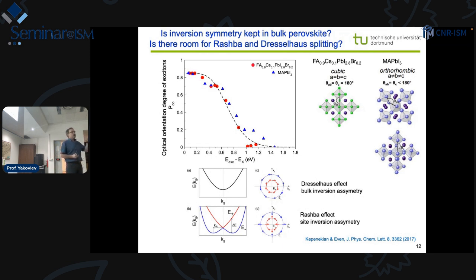And it comes in the materials in which the inversion symmetry is lost. So in this case, if inversion symmetry is lost, then the bands for the spin up and the spin down do not have the same energy. They are split in energy. And this splitting should have strong effects on the spin relaxation. But it is also discussed that such a splitting may take effect on the recombination, because you go to quasi-indirect